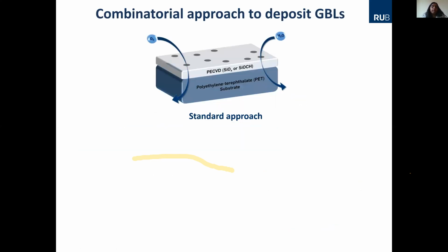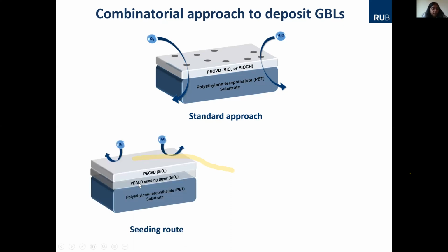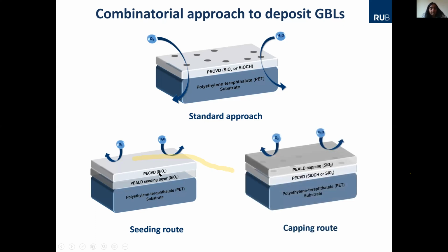So for example, a standard approach would be, okay, take a PET substrate and then coat CVD SiO2 and protect the underlying PET bottle or your substrate. On the other hand, you can think of having a very thin layer of ALD of maybe 1 or 2 nanometers, and then you're making sure that this underneath substrate is completely free of any pores, or at least there's no seepage, and then you have the PECVD coating. The other option is that you have a PECVD coating like this, and on that you cap it, okay? So these are different approaches one can see, seeding and capping routes, where you can effectively block these pores and make sure the OTR values are at the high end.